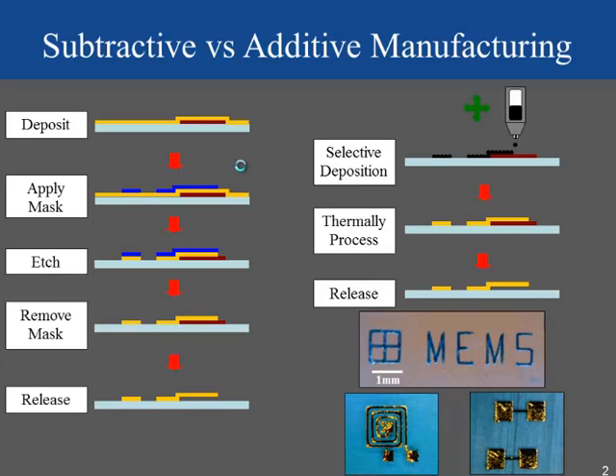Now, to compare this with conventional microfabrication shown on the left, traditionally with subtractive microfabrication, for each device layer, the entire substrate is coated with the material, and then a lithography mask is placed on top to protect a portion. The unwanted material is etched away, and then the mask is removed before proceeding to the next step. With inkjet printing-based microfabrication, a liquid precursor material, or ink, is selectively patterned onto a surface, and after deposition, typically some post-processing is required, in our case thermally, to render the precursor to its final form. And this obviously requires different deposition and precursor materials.